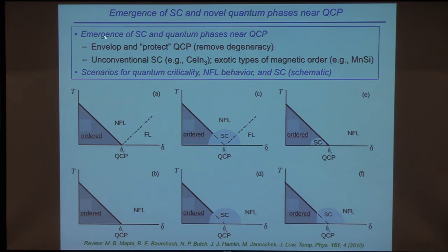Let me just say that you also find the emergence of superconductivity and other quantum phases near the quantum critical point. And so the way I kind of think about it is that these phases will envelop and protect the quantum critical point by removing the degeneracy, which I presume would be associated with these order parameter fluctuations near zero temperature. And so what you actually find in many, many cases is unconventional superconductivity, for example in cerium indium-3 and many high Tc superconductors, and exotic types of magnetic order as found, for example, in manganese silicide under pressure.